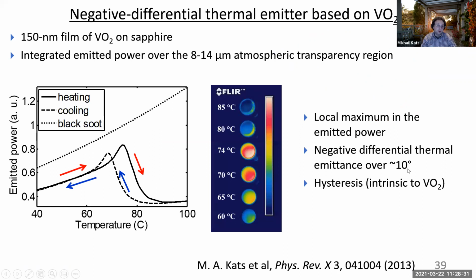And then, early on, this is actually while I was still a graduate student in Federico Capasso's group, we did our first measurement of this type. This is before we had the fancy calibration of thermal emission measurements that we have now. But here is the emitted power versus temperature of just a thin film of VO2 on sapphire. And you can already see that this is very, very strange, right? As you increase the temperature, the emitted power goes up, and then it reaches a maximum, and then it goes back down, and then eventually it starts recovering back up again.